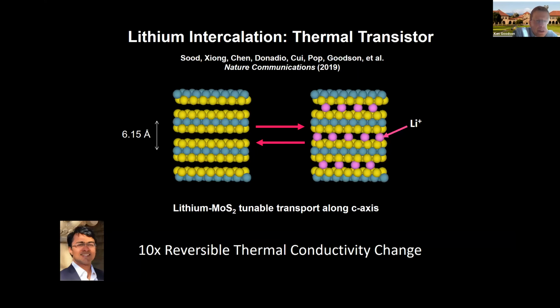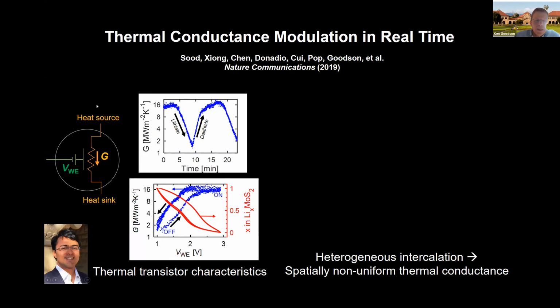The challenge with this measurement, and this is really a credit to Aditya, who had done the measurements earlier on the diamond that I mentioned, is that he was able to develop an in situ measurement where you have the thermal conductivity measured as a function of time as you lithiate and bring in the lithium atoms, and then as you delithiate, and also as a function of voltage, as you change the concentration of lithium ions and also change the conductance. The conductance you'll see is going up and down as you reduce the lithium ion fraction. There's a little bit of hysteresis going on here. And he actually did scanning of this in real time as the lithium ions were coming into the structure.